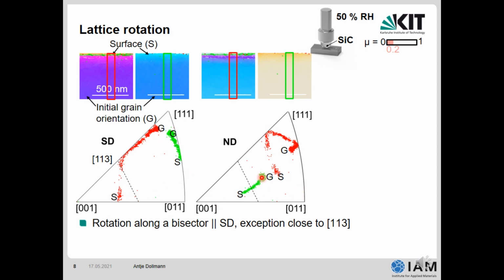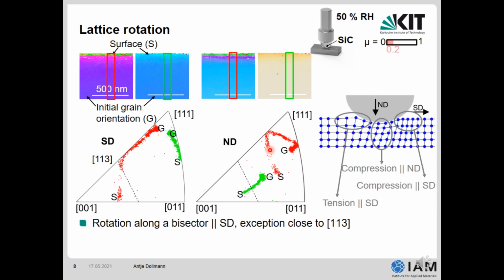Here we can see that it's rotating in the green grain from here to here, and in the red grain it's reflected at the bisectors. So here one time, here a second time, but this is quite normal based on the projection. I usually ask myself which direction is the responsible one for the twin formation, and therefore I have a simplified model which you can see here.